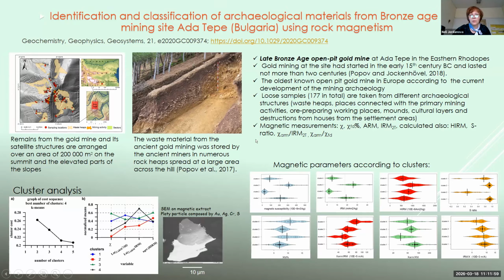And we also constructed different grain size proxy ratios. Taking this large data set, we carried out a cluster analysis to obtain the best number of clusters which can describe the variations in the data set. So we defined 4 clusters, and here on the graphs on the down right corner, you can see the distribution of different magnetic parameters according to the cluster number.